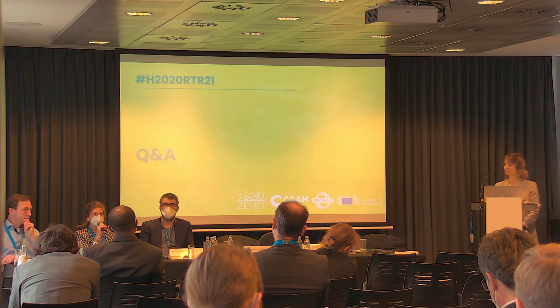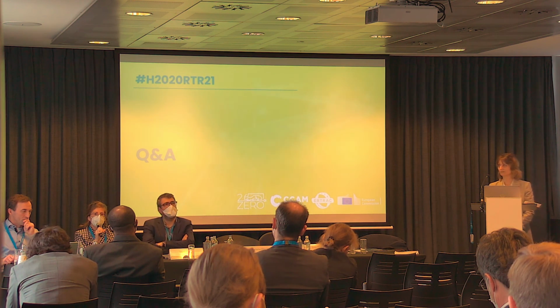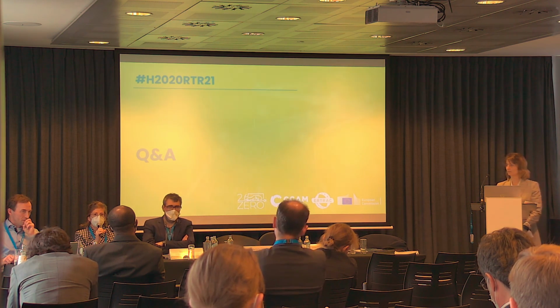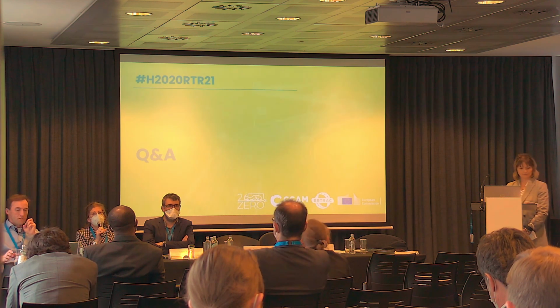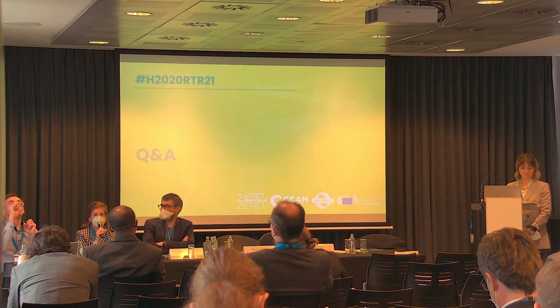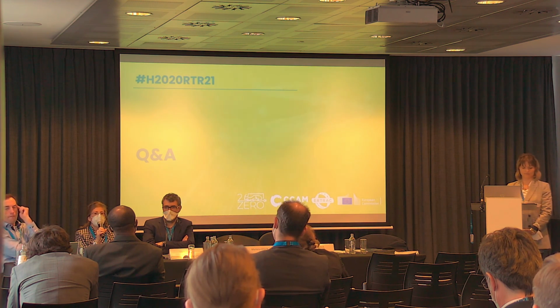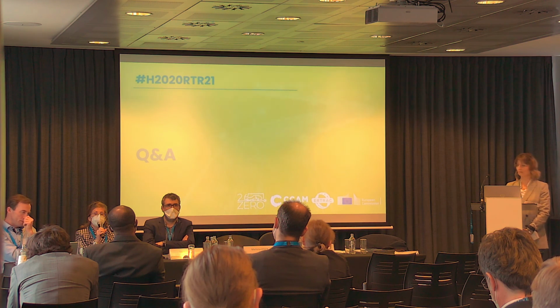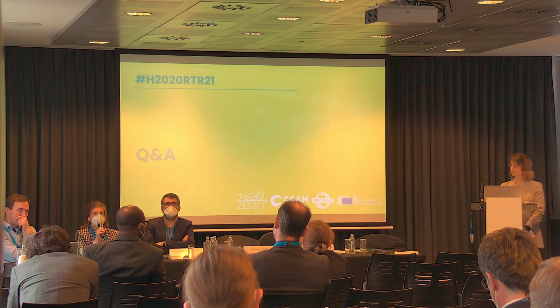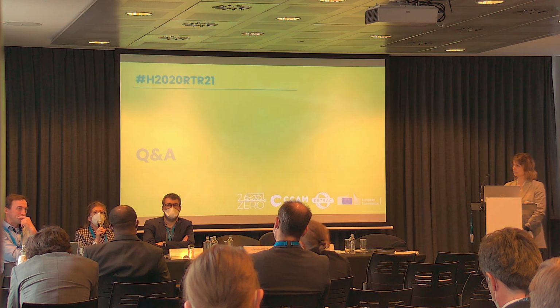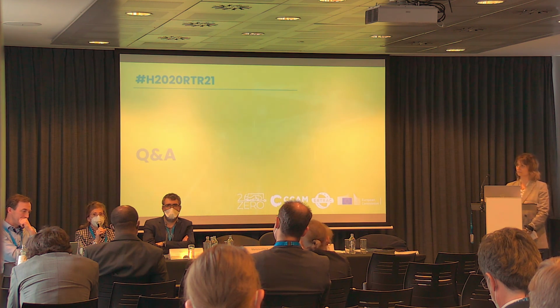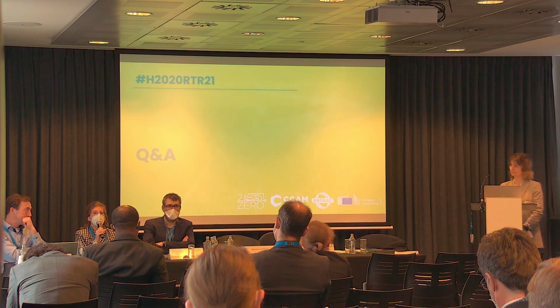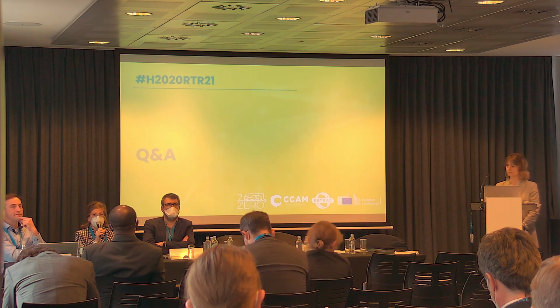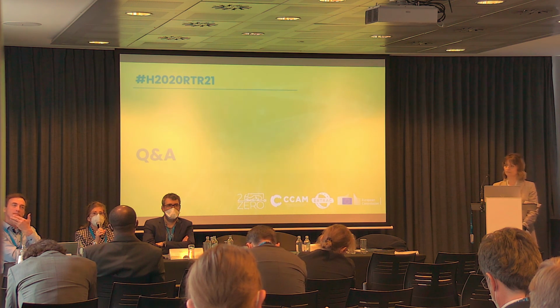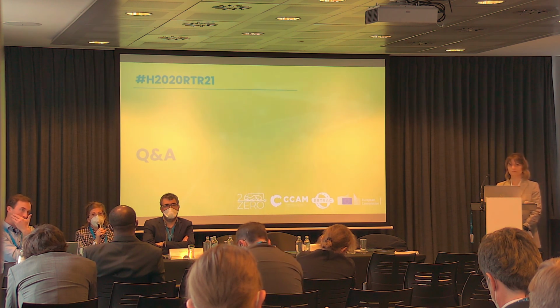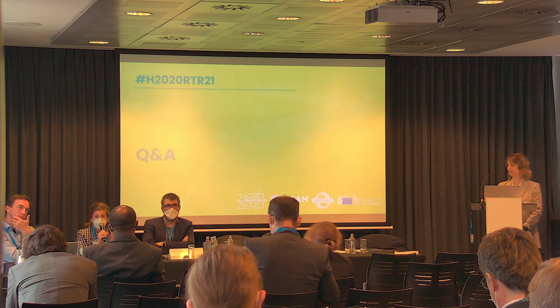Yes, within the project, as I already said, we are covering the characterization at different scales as well. So we have a capability to characterize not only the material and the cell, but also the electrode. For instance, there are some partners with the capability to perform tomography measurements, and they can also monitor online the evolution of the thickness swelling along the charging and discharging. So having this information and comparing it to the simulation results, for instance, in the microstructure with the DEM approach, is the way we validate the codes, in particular for these specific phenomena.